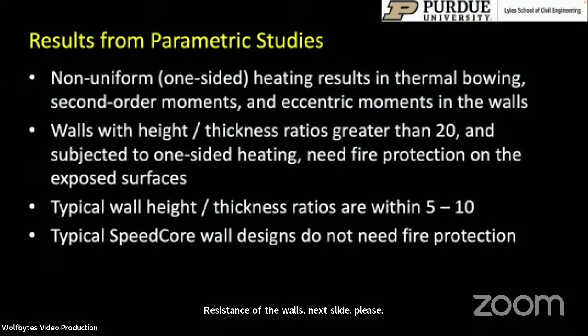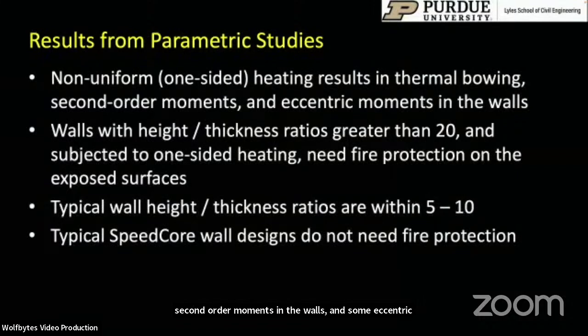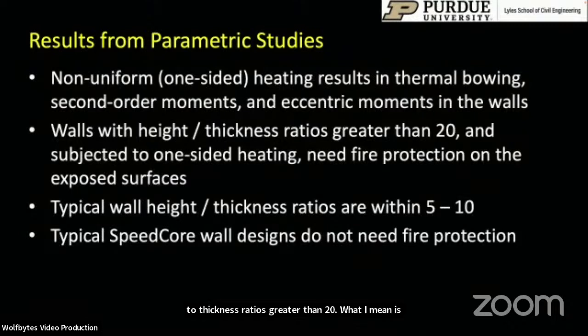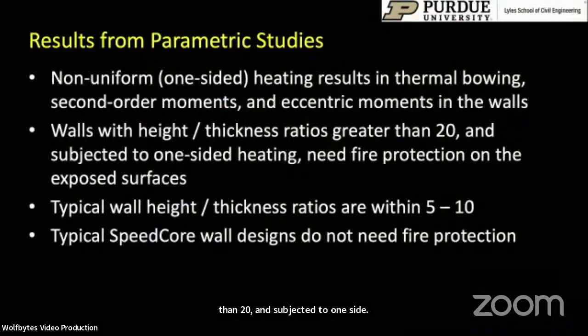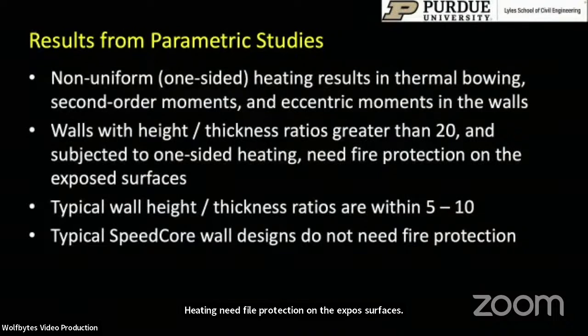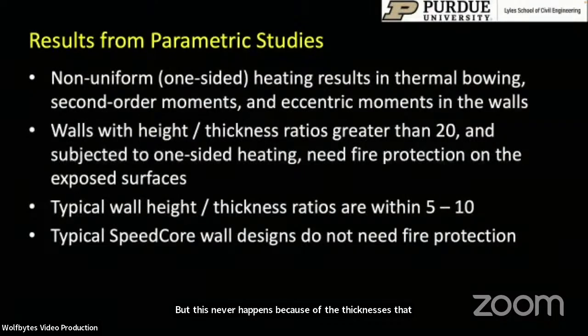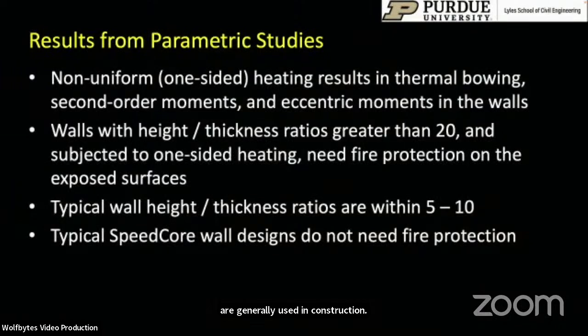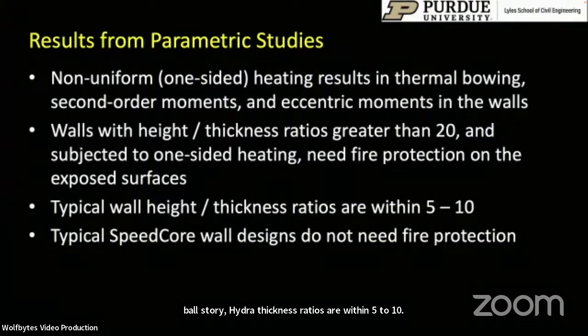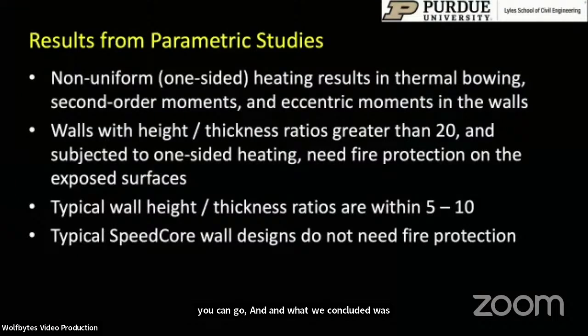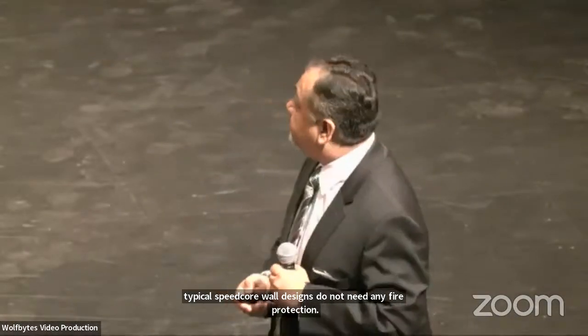We also conducted studies on non-uniform or one-sided heating, which we found results in thermal bowing, some second-order moments in the walls, and some eccentric moments as well. Walls with height to thickness ratios greater than 20, what I mean is story height divided by wall thickness ratios greater than 20, and subjected to one-sided heating, need fire protection on the exposed surfaces. But this never happens because of the thicknesses that are generally used in construction. Typical wall story height to thickness ratios are within 5 to 10. So this is just providing a theoretical limit on how far you can go. And what we concluded was that the typical SpeedCore wall designs do not need any fire protection. They can be designed unprotected.